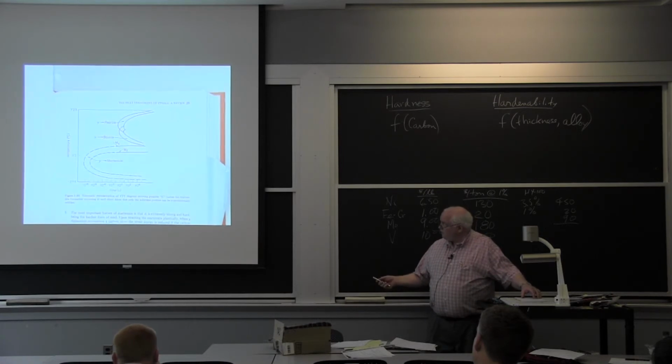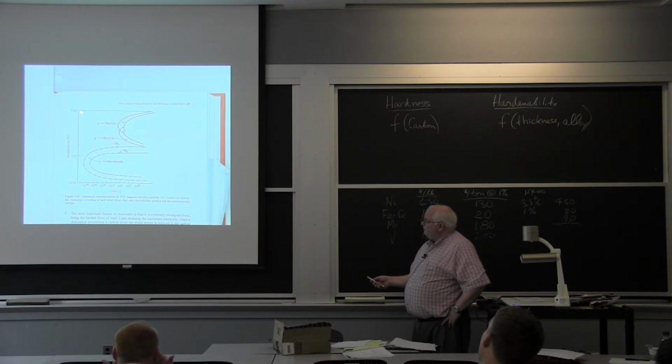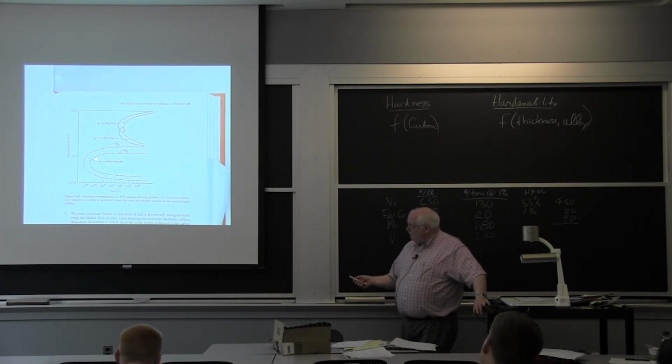Since we have a couple of minutes before I start a lot of things. This martensite transformation, this is this continuous cooling curve. This is in degrees centigrade, so that's 723, which is, I don't remember, 1200, 1300 Fahrenheit. Anyway, if you don't want to get pearlite and bainite, you have to cool down, if it has no alloying element, within a second. And the martensite is what we call a diffusionless phase transformation. You don't have to move atoms around. It actually is a shear of the crystal. It's called an athermal phase transformation. And so if you wanted to beat the martensite, you've got to cool down in something like 10⁻⁷ seconds, which is basically the speed of sound in the crystal.